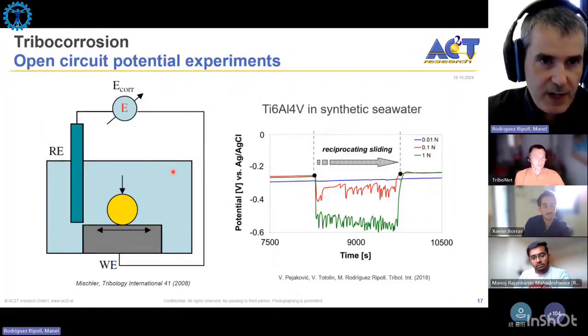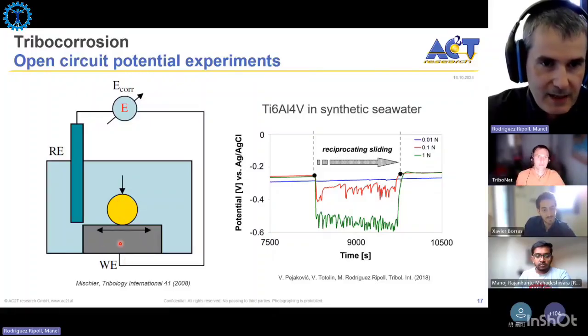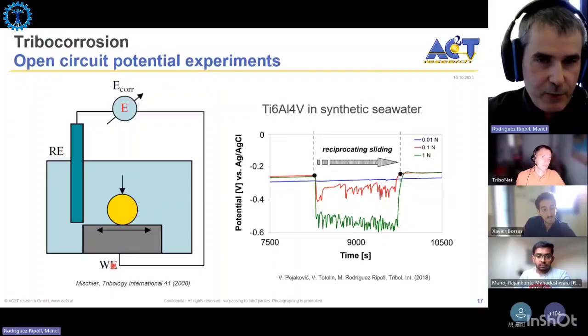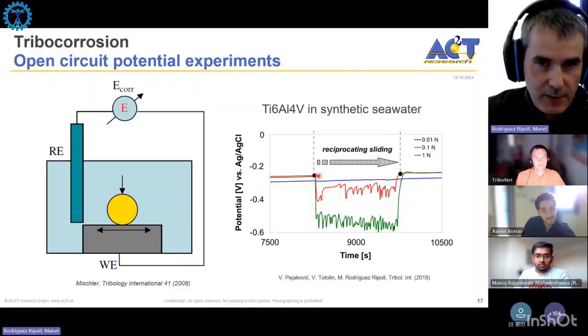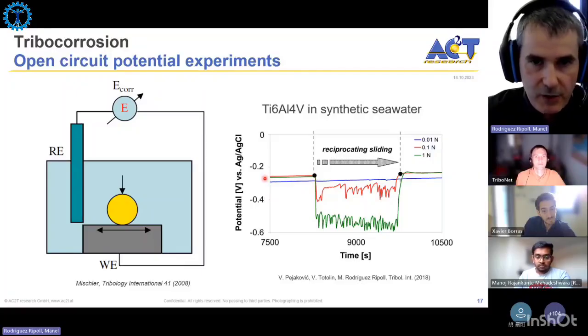So we do the same experiment as before. We have a ball, a plate, and everything is sliding. Now the only difference is that we measure the voltage between the reference electrode and our sample. Then we can track this spontaneous potential that is built by this metal, which is the open circuit potential. And we can see that before the sliding, it's stable, has a certain value.